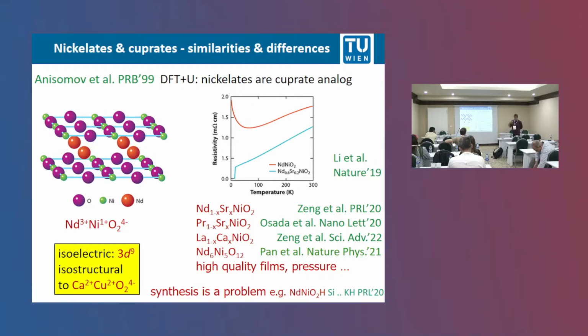Okay, now let's go to the theoretical modeling, and let's start with the very basics. So that is the crystal structure. It's identical, the infinite layer structure, to the arguably simplest but certainly not best cuprate superconductor, calcium copper O2. Here you have the nickel oxygen 2 layer, and then you have a neodymium or other rare earth spacing layer, and this pattern is continued or repeated ad infinitum.